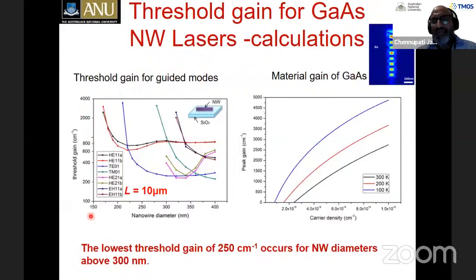In fact, I'm not plotting from 0 nanometers here. I start only plotting from 150 nanometers here. But this is also dependent on which optical mode is lasing. You can see typically 250 to 300 nanometer diameter nanowires, for a nanowire of about 10 microns long sitting on a glass substrate, is the ideal diameter to be able to make these lasers. So again, simulations are really playing an important role, and we do FDTD simulations, finite difference time domain simulations, mainly using numerical methods. For example, this is the peak gain as a function of the injected carrier density. Again, higher carrier density is needed if you're operating these lasers at higher temperatures, which again shows that it's important for us to be able to do these calculations and design the right kind of devices in order to make these lasers work.